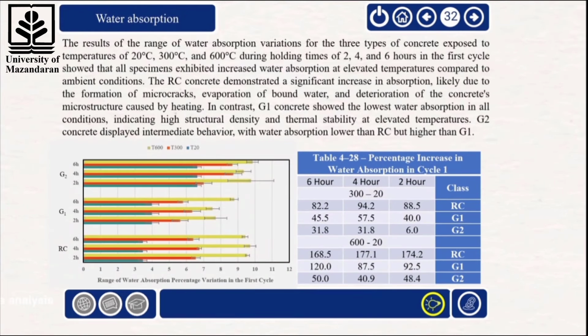Water absorption. This diagram illustrates the range of water absorption variations for 3 types of concrete: RC, G1, and G2, at temperatures of 20, 300, and 600 degrees Celsius, with holding times of 2, 4, and 6 hours during the first thermal cycle. At elevated temperatures, all specimens exhibited higher water absorption compared to ambient conditions.